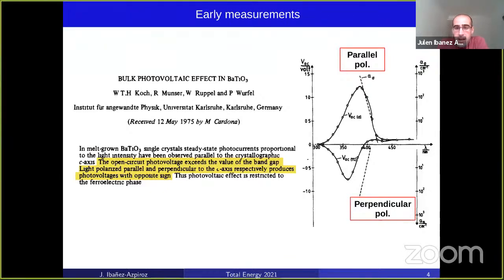And besides the large value of the photovoltage, there is one important thing to notice here, and it's that for different polarizations of the light, one can attain photovoltages that have opposite sign. That is, current will flow in opposite directions depending on the polarization of light. And even more, if we restrict to a given polarization, the sign can change as a function of frequency. So in this sense, it's an effect that has a large degree of freedom.